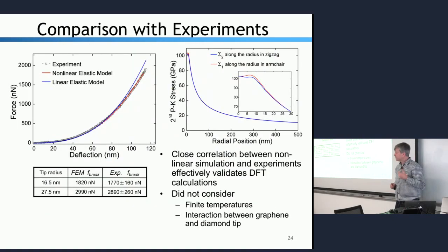Right? So the nice thing is now when we compare to experiments, we actually get a much better, and this is now, there's really no difference at low deflection, but at high deflection we actually see there's a significant difference between the models once we do these higher order corrections. The other thing is, again, we can plot the stress as a function of position and really look at what's going on right under the tip.